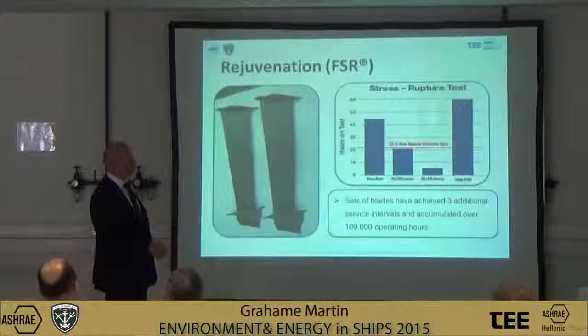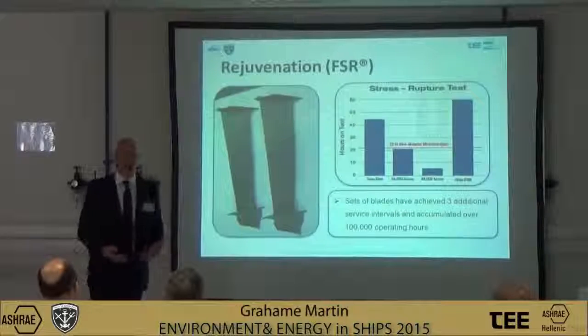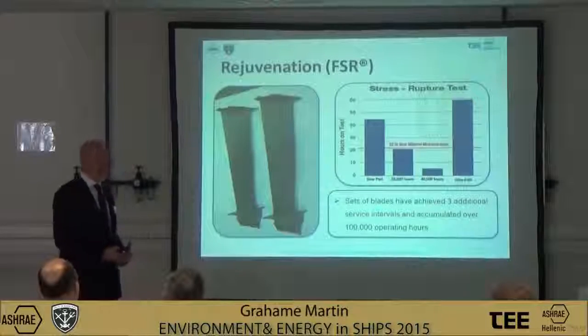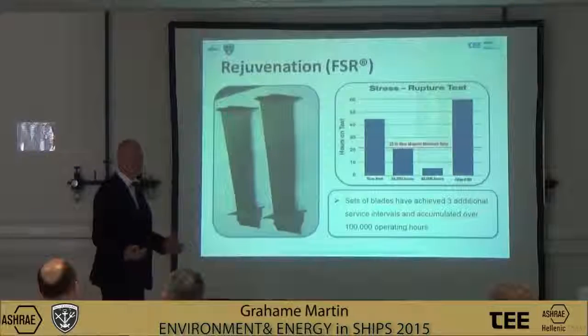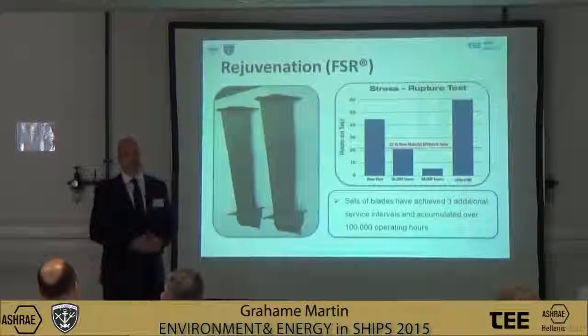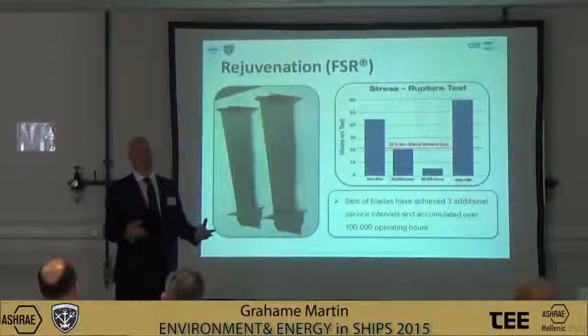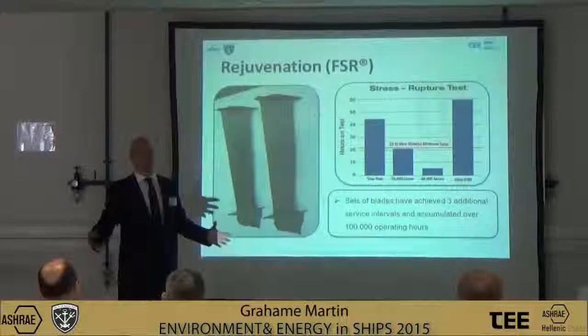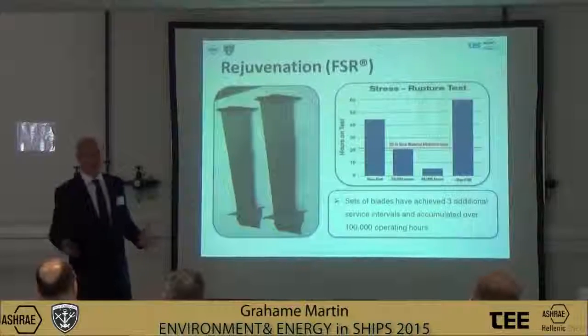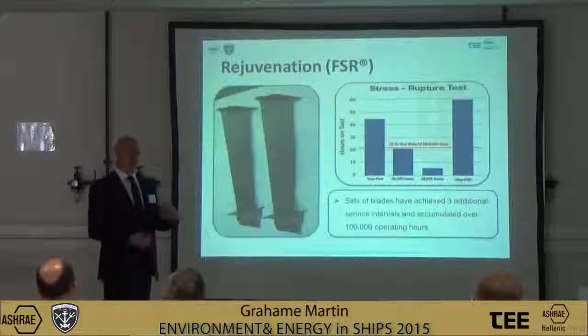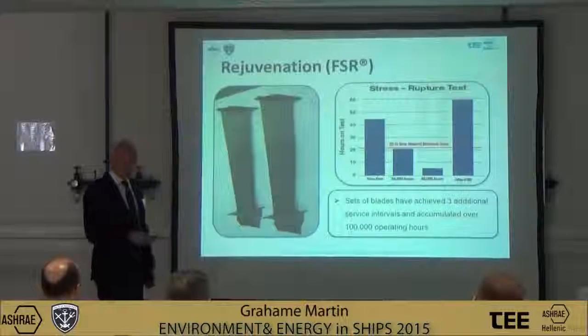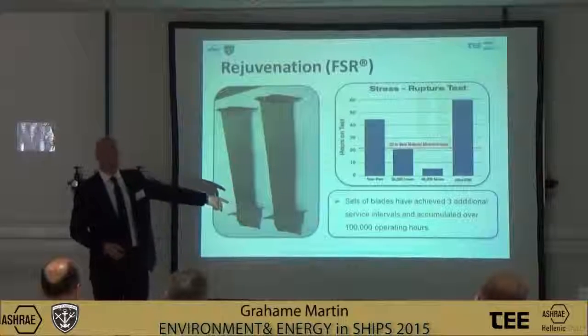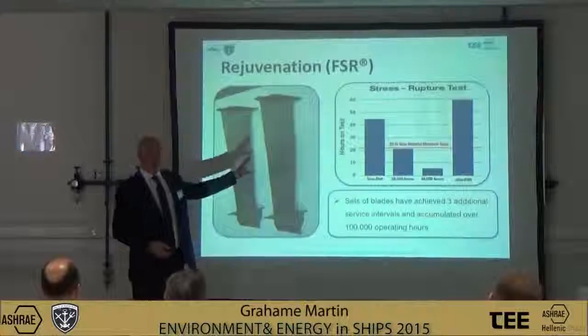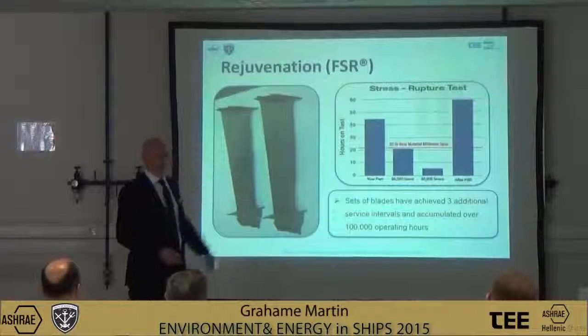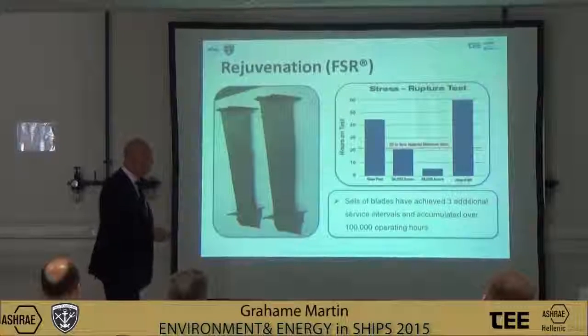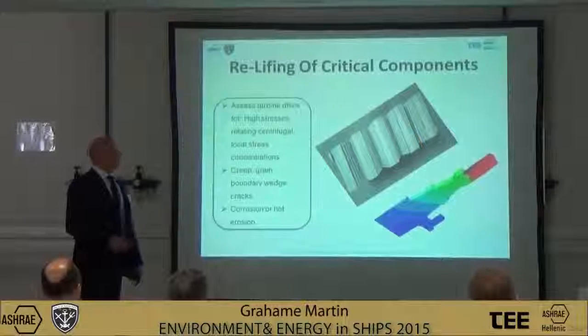And then again, once you've had the full rejuvenation process, the strength and the realignment of the grain is restored to the blade. So effectively, if you hear the term creep, which means the blade is basically getting bigger, longer, you're losing the tolerances, we can recover that through this process, up to 100,000 operating hours. This is not a new process. This process has been going on for the last 25 years.